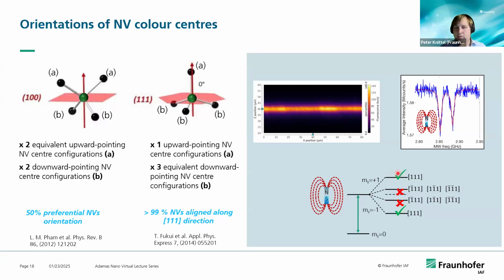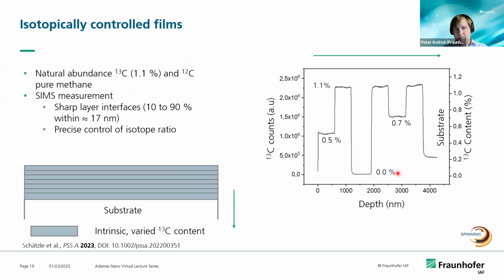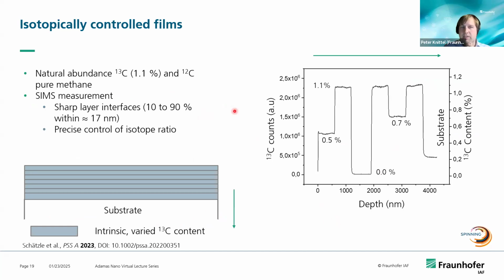Again, I've shown you already that the amount of nuclear spins can be controlled. But what is also possible is that you actually can not only produce diamonds that almost contain no 13C nuclear spins, but also something in between. And this is of importance if you think about computing applications where you actually make use of the nuclear spins in the surroundings. So you can control your spin bath very nicely using this growth approach.